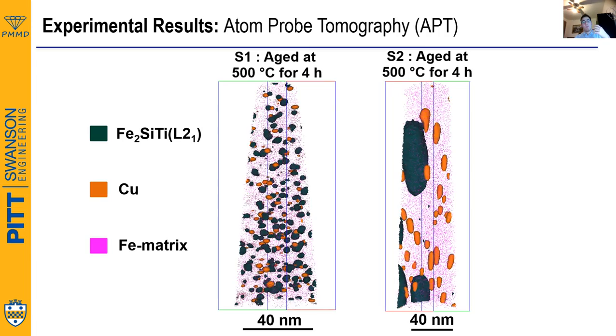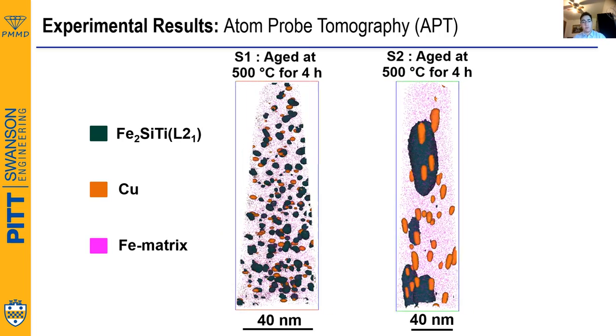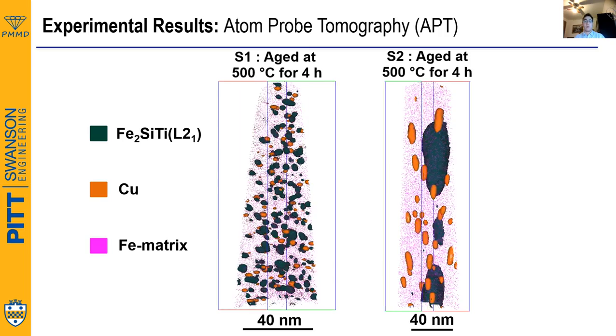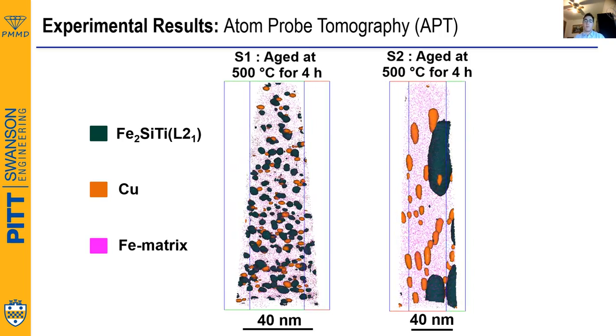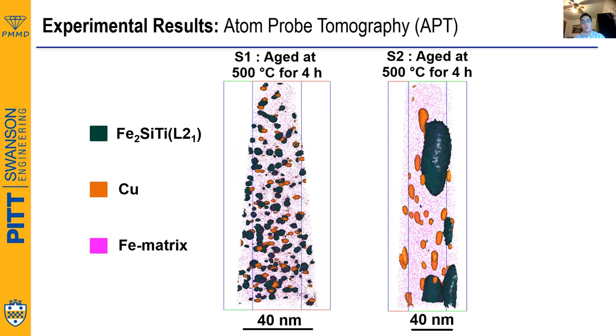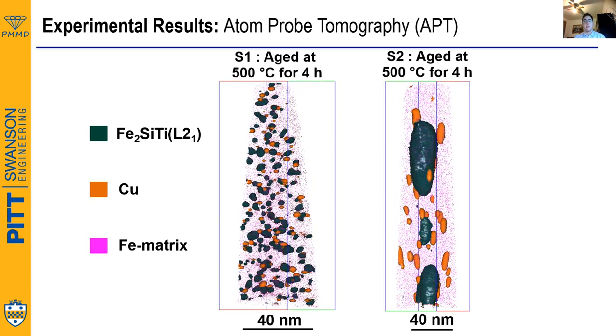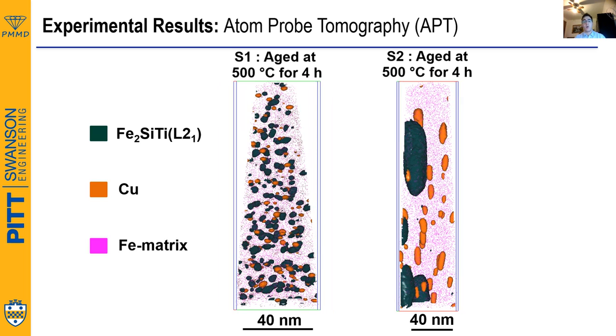In order to fully explain this hardness difference, we need to look deeper into the microstructure. This is allowed by atom probe tomography. Here you can see 2 needle samples of S1 and S2 detailing the existence of both L21 and copper nano-sized precipitates. These images clearly show a distinct volume fraction and size between the precipitates in both samples. S1 has a much finer and more dispersed population of both L21 and copper than S2. These then, by Orowan and Hall-Petch strengthening theory, can explain the difference in hardness in the aged condition shown in the previous slide.